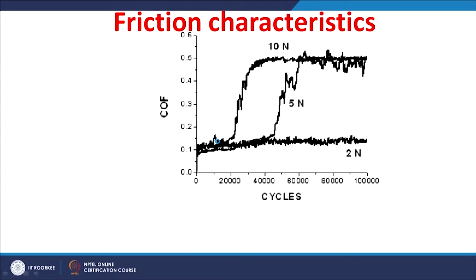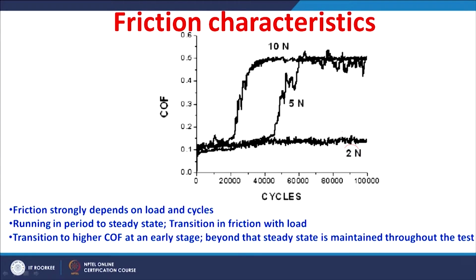Let us understand the frictional characteristics as a function of the fretting duration as well as the load applied. The fretting shows that friction is strongly dependent on both the load and the number of cycles. At a lower load, the coefficient of friction falls to a very low value of around 0.1 in around 20,000 cycles, and then remains almost the same throughout the test up to 100,000 cycles.